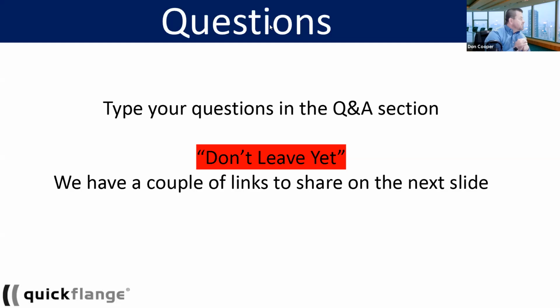Any history of failures with Quickflanges, Phil? Yeah, absolutely. We have had history of failure. Of course, we have. As I mentioned earlier, it's generally technician error, should I say? Not failure. That's wrong terminology. The biggest one we had was on a 10-inch pipe, where the technician cut the pipe so off square it missed the first groove. So although they still tried to install it, naturally it didn't get the sealing capacity, and we had to just cut the flange off and put a new flange on.